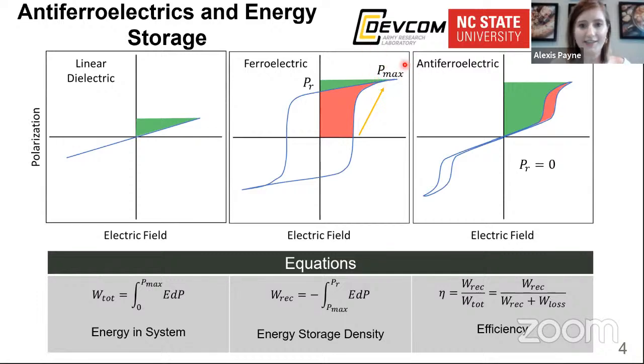Ferroelectrics, again, as you increase the electric field, you get an increase in the polarization till you reach the max polarization, P max. But as you take this electric field away, you come back to the remnant polarization. So no electric fields being applied, but you still have polarization. And then on the far right, we have our antiferroelectric. And it's characterized by a polarization electric field loop that has a remnant polarization of 0, but still is a really high max polarization.